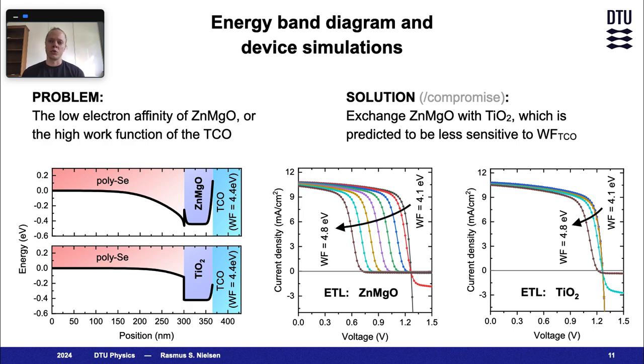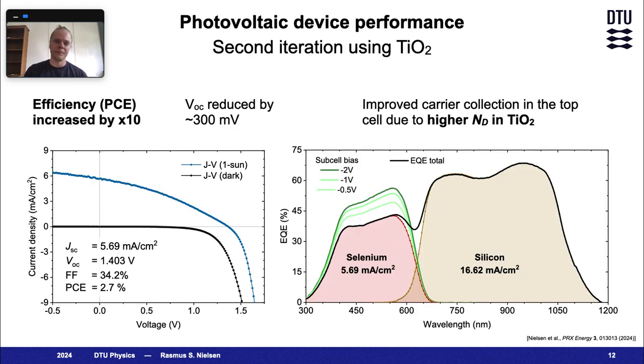Now, given that TiO2 is a workhorse in many other thin film PV devices, we investigated whether or not this contact material would be less sensitive to the work function of the TCO. This is indeed the case, but the conduction band offset with selenium is no longer ideal. Guided by these device simulations, we replaced zinc magnesium oxide with TiO2, and the efficiency increased by an order of magnitude. Now, the open circuit voltage dropped by 300 millivolts, but this was expected given the cliff-like conduction band offset between TiO2 and selenium.